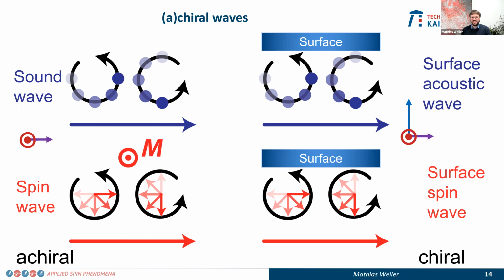I don't have published data, and I didn't want to show a lot of unpublished things here. It works. So the symmetry of the bulk acoustic waves, in the simplest case, your wavelength is set by the thickness of your piezoelectric multilayer stack. You typically get either pure shear strains or pure compressional strains, right? And then you can take the very same symmetry arguments that have already been developed by Kittel, and apply that, and by that calculate what the driving field should be. What we see in experiment is that this describes it quite well still, also for the bulk acoustic wave.